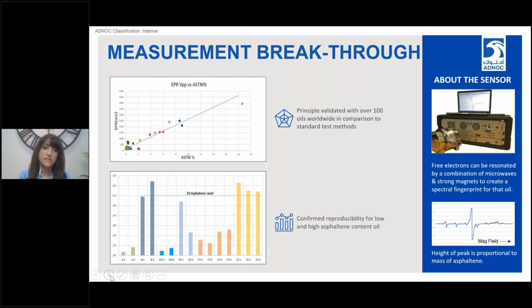We also wanted to see if the sensor has a limitation. Can it measure very low asphaltene concentration and very high asphaltene concentration? Can it look at the range, or is there a cutoff point? And we happily found out that even at concentrations as low as 0.1% asphaltene, we can still have a clear signal, and it's a reproducible result. So you could see from the graph below that we have asphaltenes from different wells and with different concentrations, and we could still see the signal, and it is reproducible.